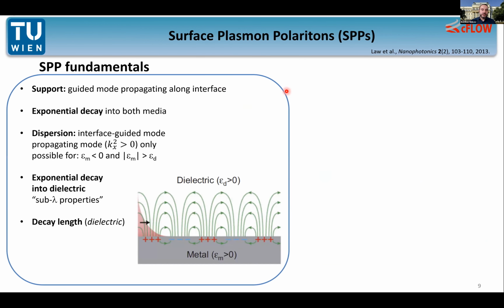So we go directly into the so-called surface plasmon polaritons. Those are the ones that are guided along the surface, in contrast to the localized surface plasmons. Maybe you know them from metal spheres, small metal particles, on whose surface you can also excite plasmons, but they're really localized. In our case, at the interface between the metal and the dielectric, the mode can propagate along it. Some important features, besides the guiding of the mode along the surface, are that we have an exponential decay of the electric field into both media. So into the dielectric and into the metal, the field decays exponentially, but in a different way, of course, depending on the actual value of the permittivity.